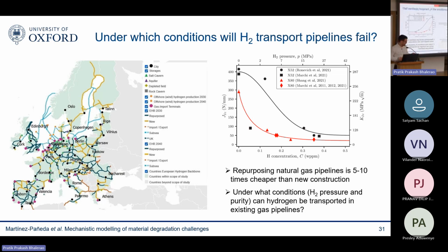And you can see here, this is the European hydrogen backbone. So these are the pipes: the blue ones are the ones that are repurposed, retrofitted, and the yellow ones are the ones we're going to build. You can see places like the UK, we're basically hoping that we'll use the pipelines that are already there, because that will save, I would say, basically an order of magnitude in cost. So it will be 10 times cheaper to do so. But as you can see in this plot here, those pipeline steels seem to be undergoing significant hydrogen embrittlement.